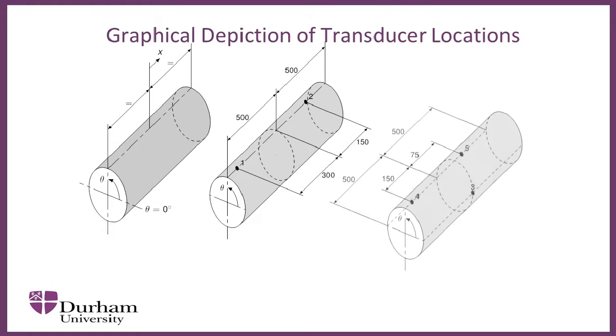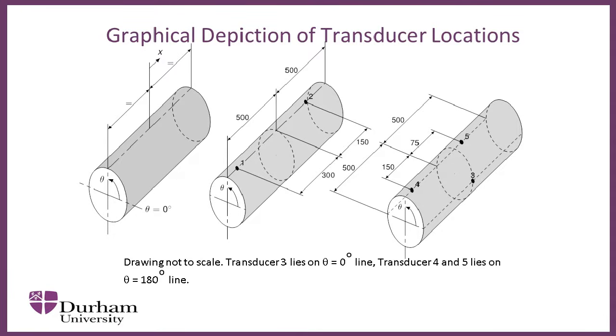So for the experimental configuration in this work, a mild steel pipe was used, which has a length of 1 meter, an outer diameter of 101.64 millimeters, and a wall thickness of 2 millimeters. The coordinate system used to indicate the location of the transducers and the holes drilled to simulate the damage is described in the figure. You can see from the figures that we put 5 patch transducers, and the locations of the transducers are also shown in the figure. You can see 1, 2, 3, 4, 5 at different locations on the pipe.